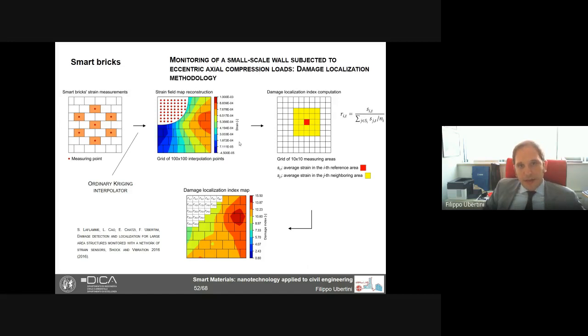We reconstruct the strain field through an interpolation procedure using kriging, that is a stochastic interpolator that's very interesting from several perspectives. And then we do damage localization through the definition of different features that essentially look for locations where the strain has large gradients, which means that probably there is a crack in that location. That's why there is a relaxation of the material around the crack. That's why there are gradients of strain there. And in this way, we try to locate damages.